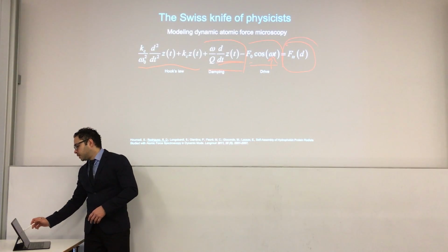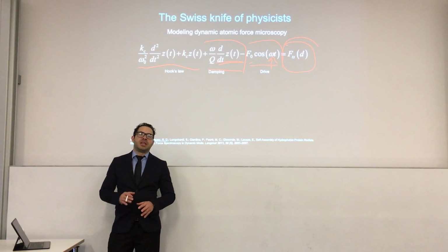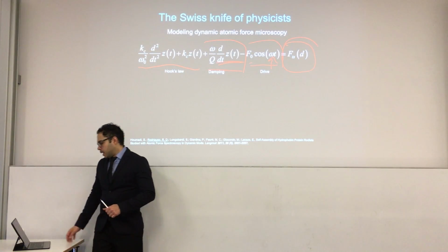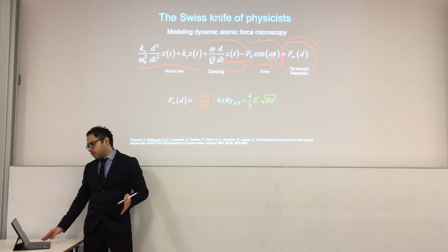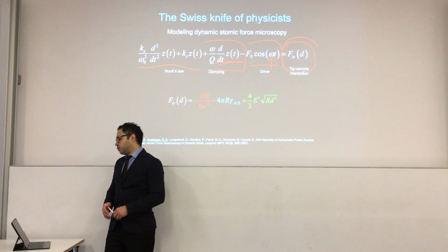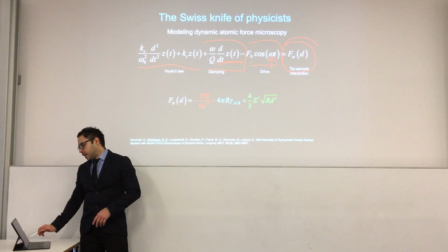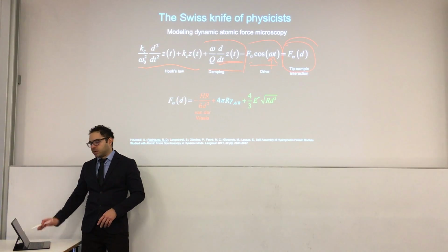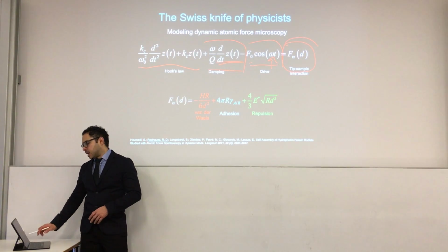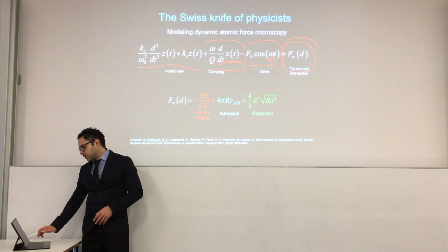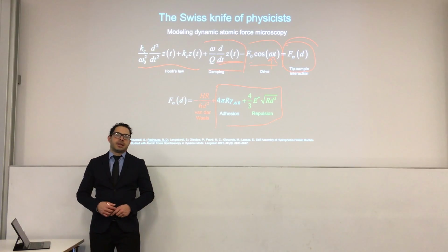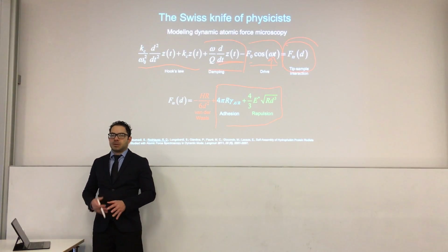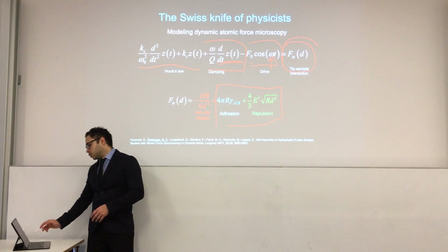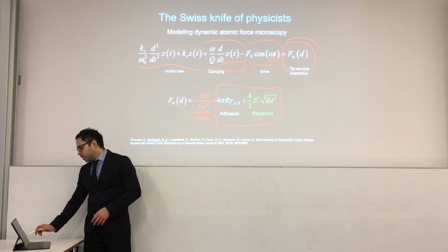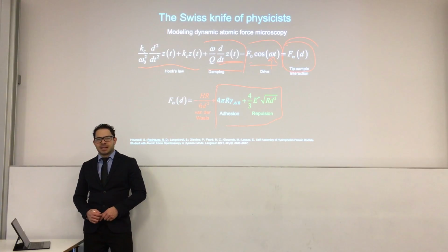The last term that you see here is very, very important. This is called the tip-sample interaction. In a very approximate way, we can describe this tip-sample interaction as being composed of different terms. The first one is a long-range interaction described by a van der Waals force. You can also have some repulsive interactions or contact interactions that are composed of an adhesion term, which depends on the surface energy of the system, and also a repulsive force, which is dependent on the elastic properties of the system.